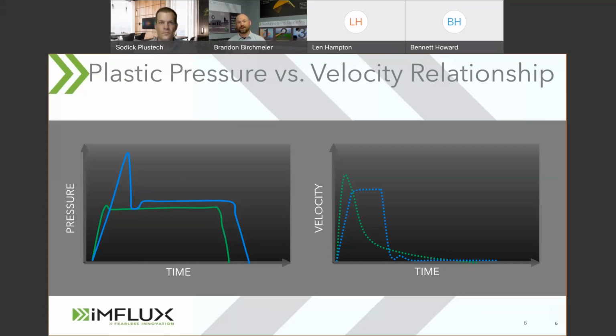But you can also get creative on the family mold side. I do not need to have very good balance in my process at all because I'm not worried about transferring. We just did a webinar not too long ago, molding a couple of bowls, a lid, and some forks and spoons. Completely different, in a 7-cavity mold. Every single cavity is very different from each other. But constant pressure allows me to mold all of those cavities without issue. I don't have to worry about all the balancing because I don't have to worry about the pressure continuing to increase on rheology-based injection speeds.